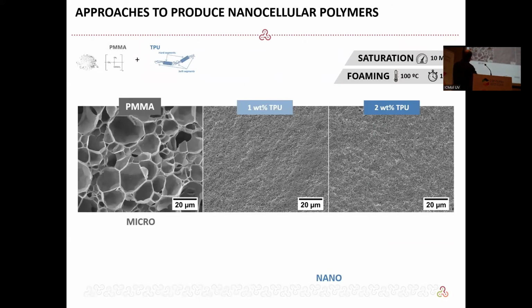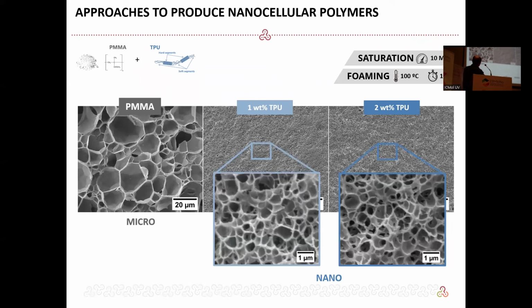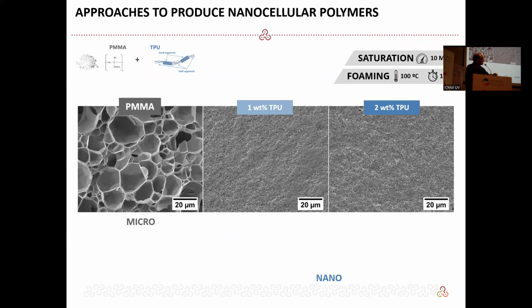I will show you just one example, which is very spectacular. Here you see PMMA, microcellular, produced with 10 MPa and foaming at 100 degrees C for 1 minute. Well, 10 MPa is a high pressure, but not as high as before. In the homogeneous nucleation, I need 30 MPa. This is a microcellular material. And these materials are produced with the same conditions, but I have introduced 1% TPU here and 2% TPU here. You see, the relative density is the same, but the cell size is much smaller. So by properly controlling the formulation, we can go from the microscale to the nanoscale using processing conditions that are easy to reach.